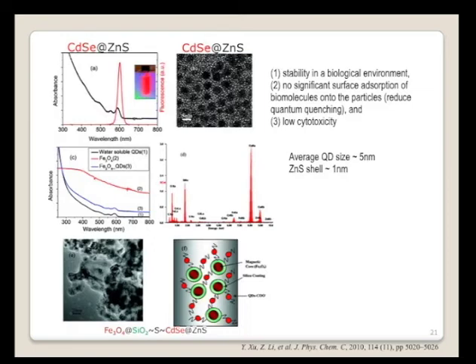This is the quantum dots under UV irradiation. We see the emission, the light is a red light. Wavelength is around 600 nanometers. Right side image is a TEM. You can see this is the quantum dots coated with zinc sulfide. We also did the optical absorption for this material. This is water-soluble quantum dots. Because of this coated zinc sulfide layer, it became water-soluble. It's very good for the biology research.